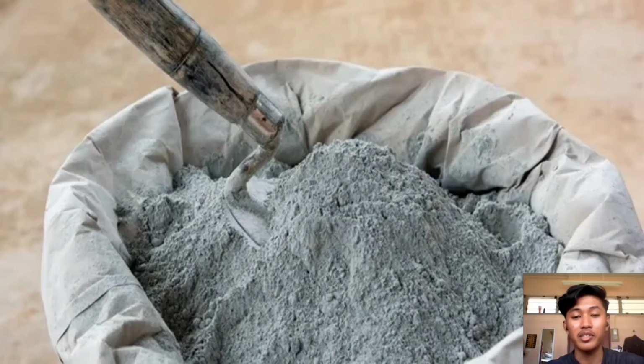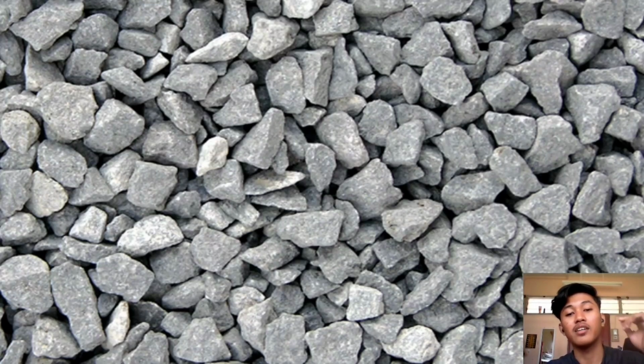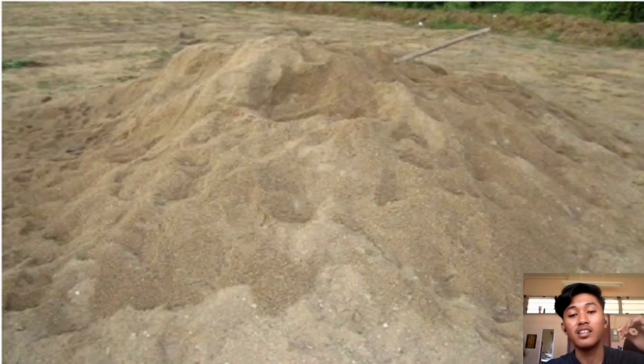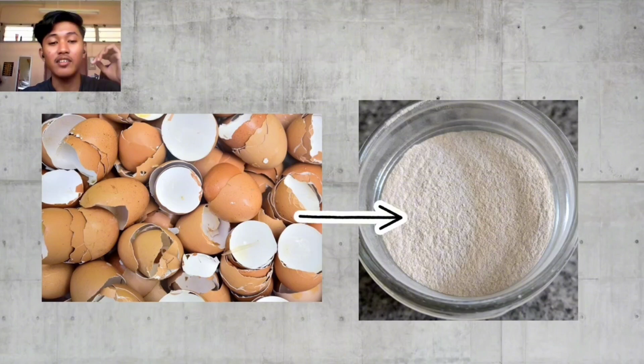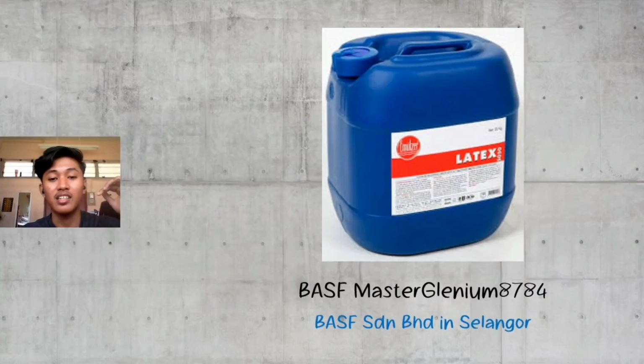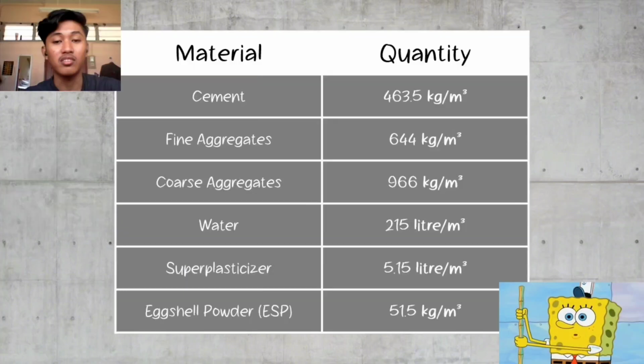So the materials that we use are ordinary Portland cement, and coarse aggregate with a size of 10 mm, which can be obtained from a quarry. For fine aggregates, we use natural sand, and eggshell powder can be obtained from any source, and it should be ground and crushed until it turns into complete powder. For super plasticizer, we use BASF MasterGlenium 8784, which can be obtained from BASF Sdn Bhd in Selangor.